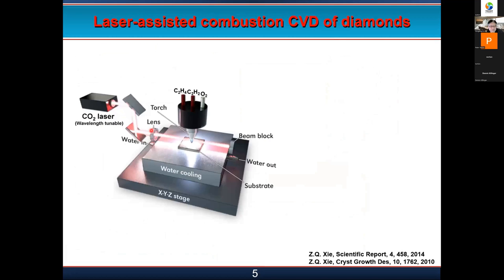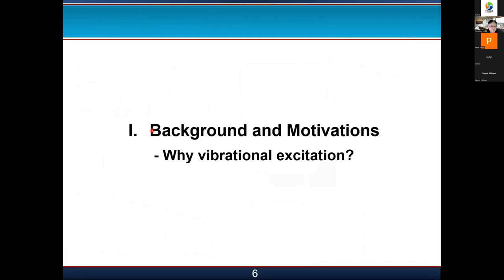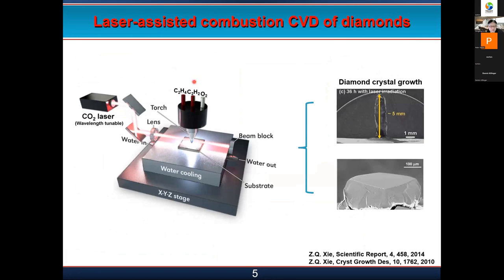In the past 15 or 20 years, what we have been doing is growing diamond in open air. We use a combustion flame, and at the same time a CO2 laser, which is wavelength tunable. We can tune the wavelengths of the CO2 laser to specific vibration modes of molecules to control the chemical reactions and to gain the growth rate as well as the crystallinity. Using this approach, we can get crystal diamond, and sometimes very large diamond crystals in terms of millimeters. It takes time, but this approach is much faster than the conventional CVD process.